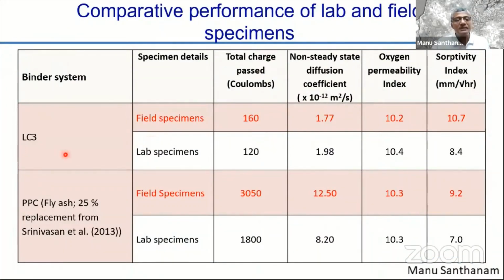You can see for LC3, the field and lab specimens are not all that different. RCPT, NT Build test, and oxygen permeability, all of these are producing results of almost the same numbers. Whereas if you consider fly ash based concrete, which was from a parallel study, not the same study, you can see that the field specimens depend a lot on the fact that you have not cured it well enough as compared to the lab specimens. So you can clearly see the difference in the case of fly ash based concrete. In other words, LC3 based systems are probably less susceptible to the problems of lack of curing in the field.